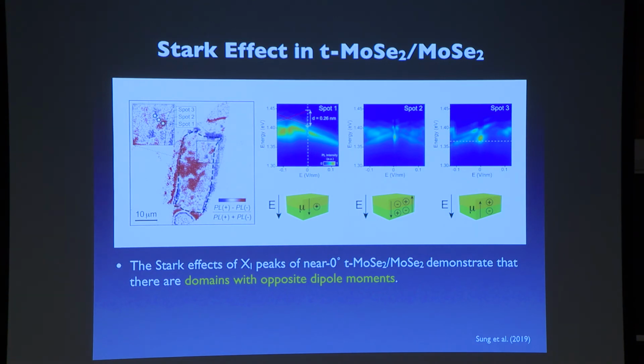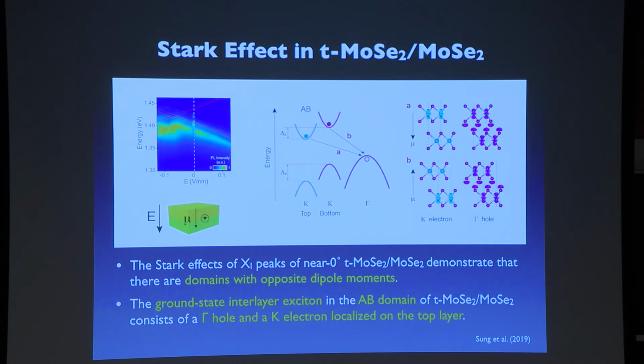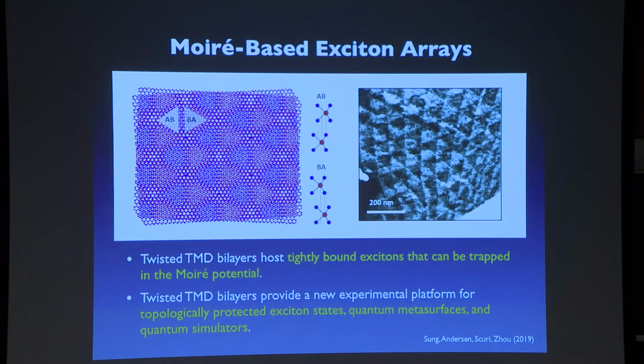And when we twist the bilayers and then generate a bunch of different domains, then you can start to generate different regions with a different dipole moment orientation. And there is a reason why it's happening, and the reason why we are seeing lots of other types of features. But the most important thing is the following. By using this particular phenomenon, we can now start to generate exciton arrays where in one particular region, the exciton is pointing one way in terms of dipole moment, and in the other region, there is an exciton pointing downward. So you can actually start to generate exciton arrays, tightly bound excitons that can be arrayed in a nanoscale fashion, and we are now trying to use that particular fact in order to make interesting devices.